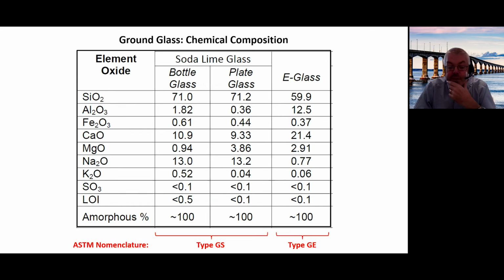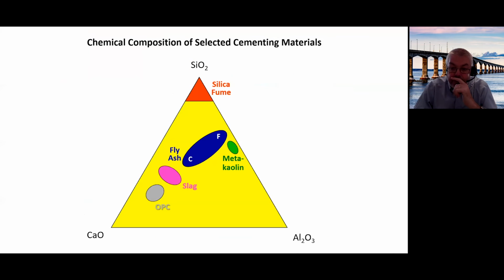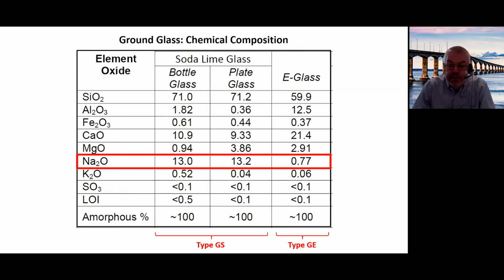Soda lime glass has been identified as type GS glass by ASTM. E-glass, which has a low alkali content, is type GE glass. They would sit here on our ternary diagram. GS is quite close to silica fume on the ternary diagram, whereas GE contains more calcium. So the alkali is a concern. It's certainly a concern if you have a reactive aggregate in concrete. If you don't have a reactive aggregate in the concrete, then it shouldn't really be a concern.